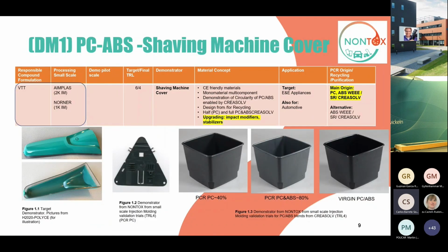As I said, let's take some of the cases and still have the time to discuss a little bit. The first one was this material where PC/ABS was developed towards a shaving machine cover. This was a material recovered by CreaSolv, both ABS and polycarbonate, and the upgrading was mainly in the direction of impact modification and stabilizers. Here, versions of half CreaSolv with content of polycarbonate and full PC and ABS CreaSolv were developed with quite good results, with some limitations when it comes to color.